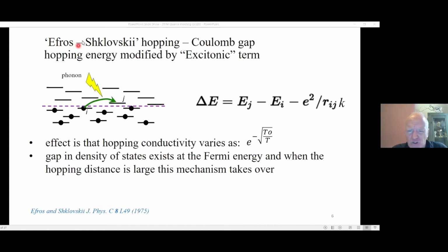When we have this Efros-Shklovskii mechanism, the energy involved in the transition is not simply the difference in energies between the two states. There's also an excitonic term. When the electron hops, it leaves a positive image charge. The positive image charge and the electron form an excitonic state, and there's a bound state correction to this energy, delta E. The correction is the Coulomb interaction between the hole image and the electron charge.